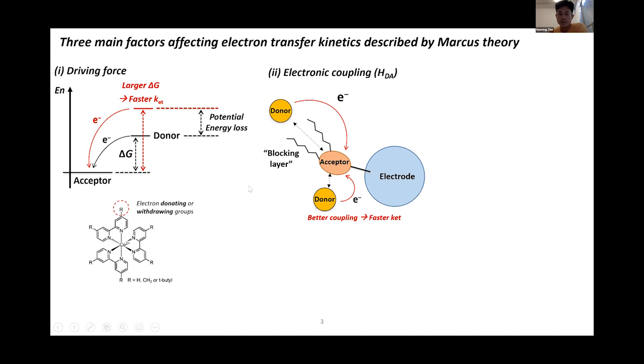Another thing is to control the electronic coupling, which is the interaction between wave functions of donor and acceptor molecules. For example, in one case there is an insulating layer keeping the donor and acceptor molecules far from each other. In that case, electron transfer is slow. In another case, if they are close to each other, for example through intermolecular interactions, they have a faster electron transfer rate through better electronic coupling.